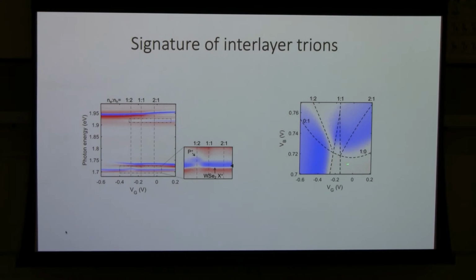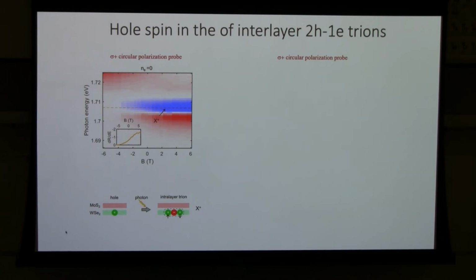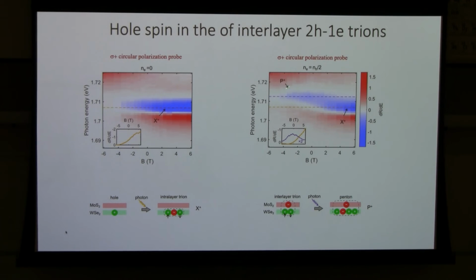But in order to establish conclusively that this is a bound trion state, it's actually better to look at the spin correlations. So first of all, let's remind ourselves what happens if you have only free holes in the system. A free hole has a spin that can be polarized with a magnetic field. I have shown you previously that if you apply a magnetic field, you can polarize the spin, and then using circularly polarized light you can see this is fully polarized in one spin, and this is fully polarized in the opposite spin. Now we can look at the magnetic field dependence for this new spectral feature.